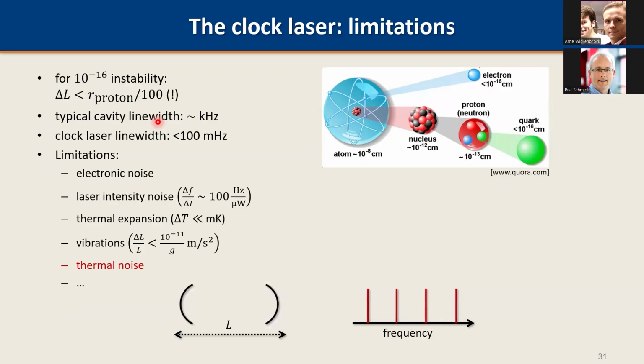Now, what are the technological challenges we have to face? It's electronic noise, because we have to resolve the cavity line width by 10 to the 6. That's not easy. We have intensity noise on our laser, and there's absorption in the coatings of our mirrors. Intensity noise means that the absorption changes, that changes the heat load absorbed by the coatings, and therefore their temperature. That leads to a change that can be up to 100 hertz per microwatt, which means that, since we put in only a couple of microwatts of laser power, we're close to the shot noise limit of the detection of the light intensity that we need to stabilize. So we're at the edge, essentially everywhere in this system.